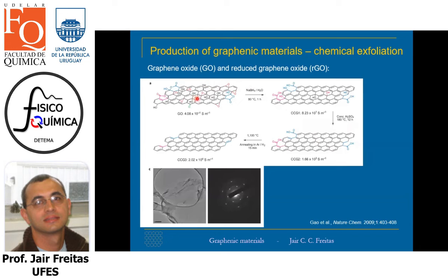So this graphene oxide can be reduced to graphene. The pristine graphene structure can be recovered, although with some defects, it's impossible to get rid of all defects. So this is not exactly graphene, it's reduced graphene oxide. But this reduction process can be followed by using solid-state NMR as well as other spectroscopic methods. So this is a method to produce a material with good thermal conductivity and good electric conductivity starting from graphite and using a reaction in liquid medium.